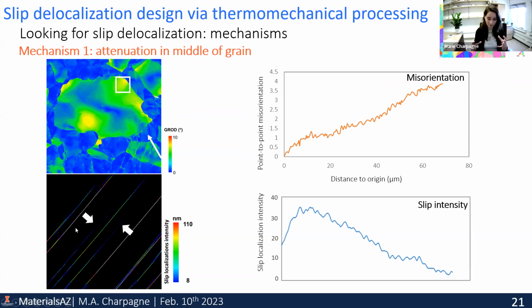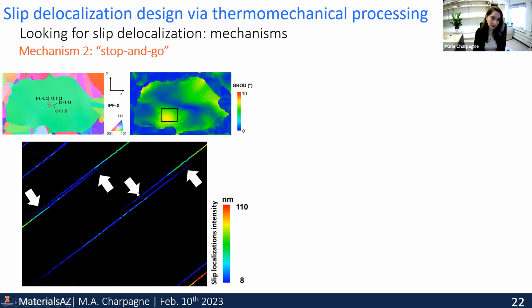But of course, we still have a fixed amount of plasticity that this material needs to accommodate. So we found a second mechanism, which we call stop and go for lack of a better name for now. Essentially, this happens again in those regions of high lattice rotations, where we see that some slip bands not only decrease in intensity, but sometimes you have the formation of another slip band of mild intensity nearby the first one and on a similar slip system. And here are two examples. So we had the first slip band here and the second one that formed after the fact. And here another one and this very mild slip band that came in right nearby.